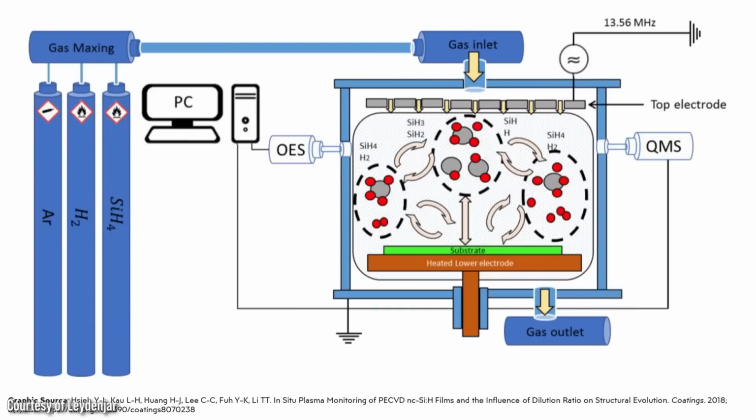I was going to ask separately about the dry anode manufacturing. Traditionally, that sounds way different than any kind of dry manufacturing process that I've ever heard. So there's that particular process. It's just a gas process, and there's not actually any liquids involved there at all. From what I hear, as you said, the incumbent technology for anode production is where you make a mixture, you make slurries, you coat it, you dry it, you calender it. But in our process, it's just copper foil, silane, and a couple of other gases, and using plasma to make this reaction on the copper surface. And it's a completely dry process, giving you the resultant anode.